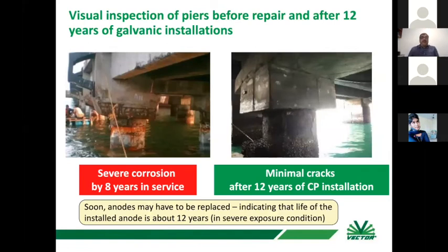Imagine, in 8 years of service life, there was significant damage. And when you repair it using sacrificial anode system, after 12 years you have very minimal cracks, not a major corrosion problem like what it was there in 8 years. So this type of repair is required. A professional approach has to be done.